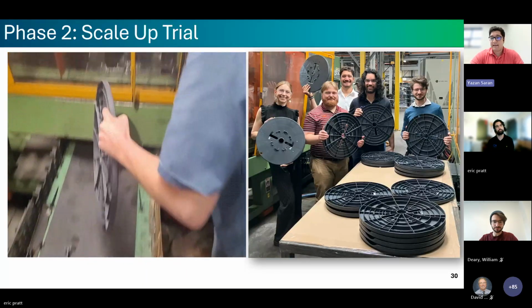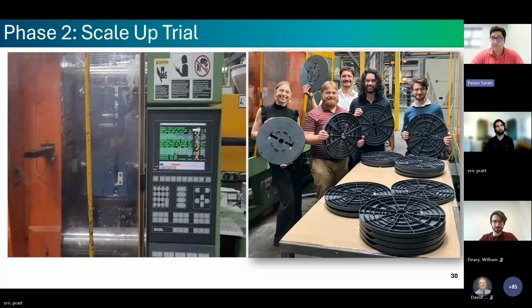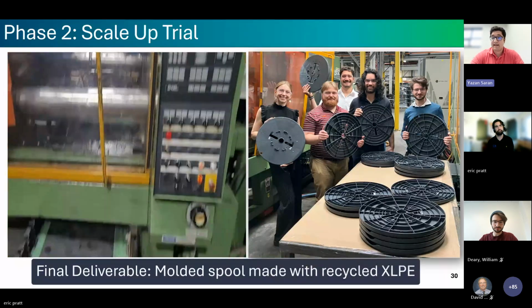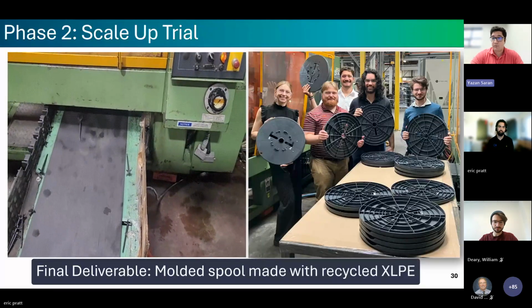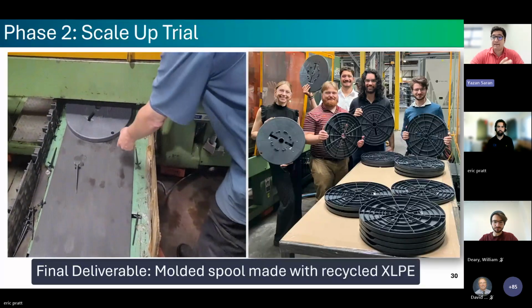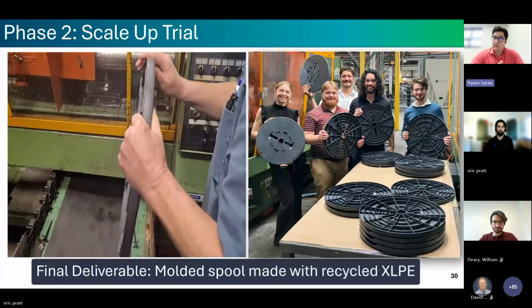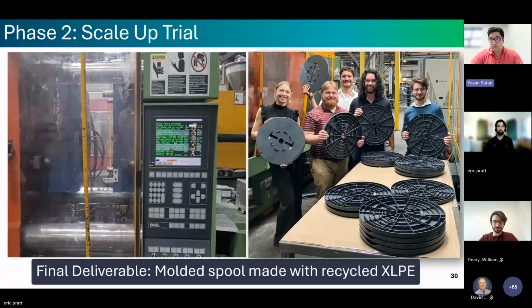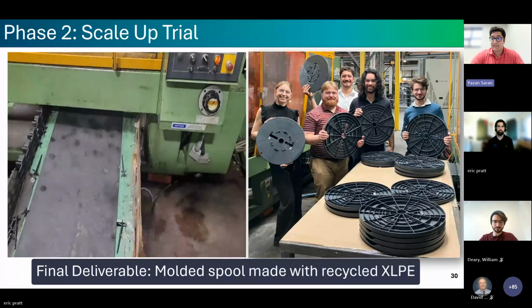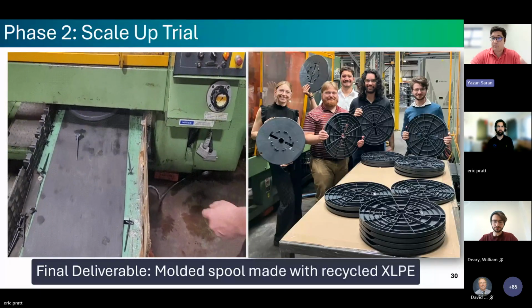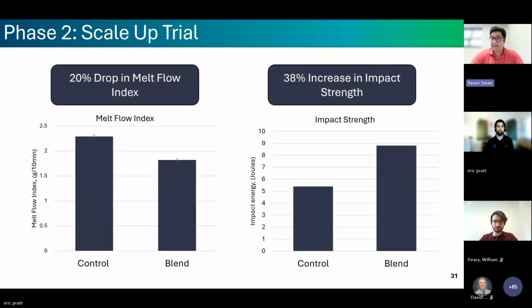This injection molding trial highlighted the success our team had in delivering on one of the primary goals we set out to achieve during phase 2 and over the length of this project as a whole, which is our molded spools. However, we weren't done quite yet, as we still needed to both characterize and test our optimal blend and conduct our reprocessing study. The first test we ran on our new blend was melt flow index, which, as previously mentioned, is crucial in helping us determine the processability of our blend.